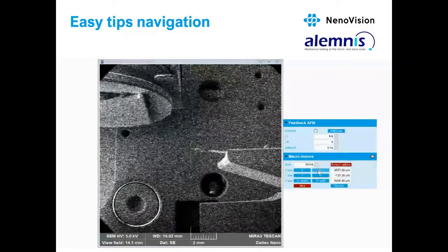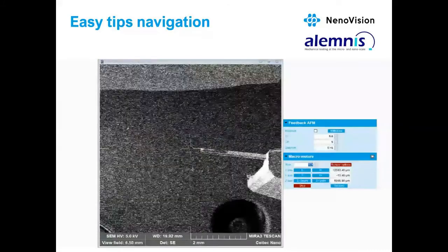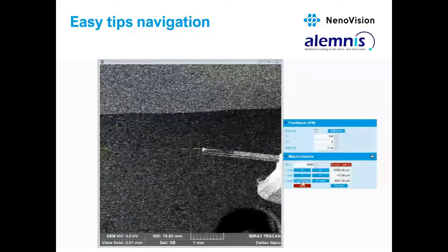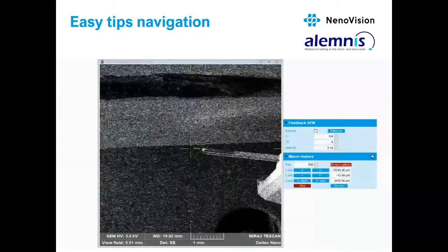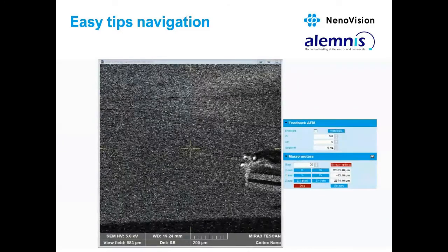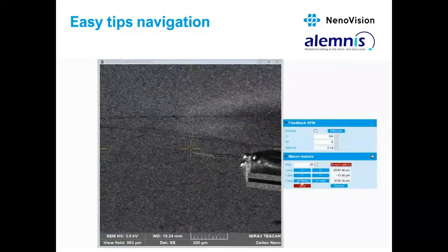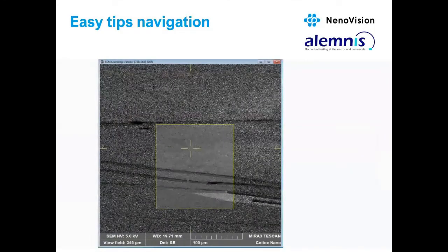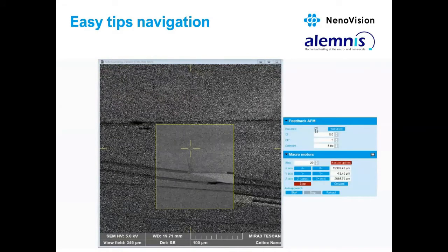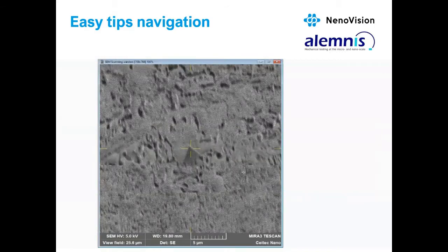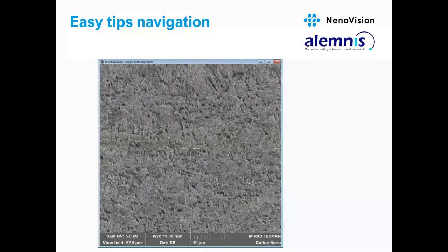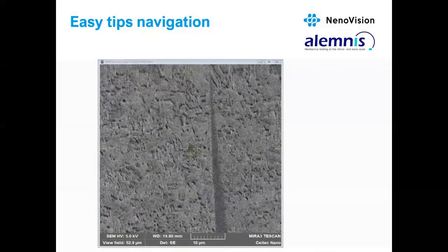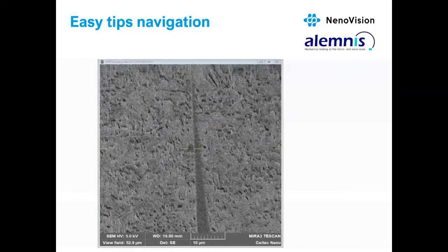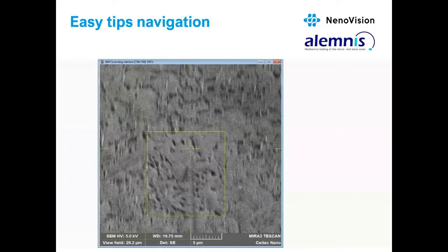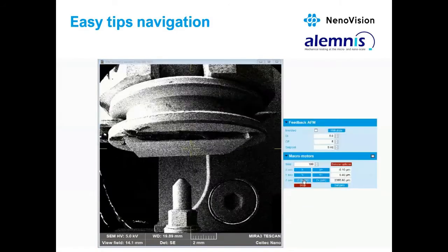So now we got really easily into the AFM probe focus. And because it's the fixed position, we just move the sample in XY axis and then slowly in Z direction. Finally, we use auto approach function to get the AFM probe safely into the contact with the sample. As the AFM tip is now in contact at the indented place, we can just measure the AFM topography of exactly the same spot.